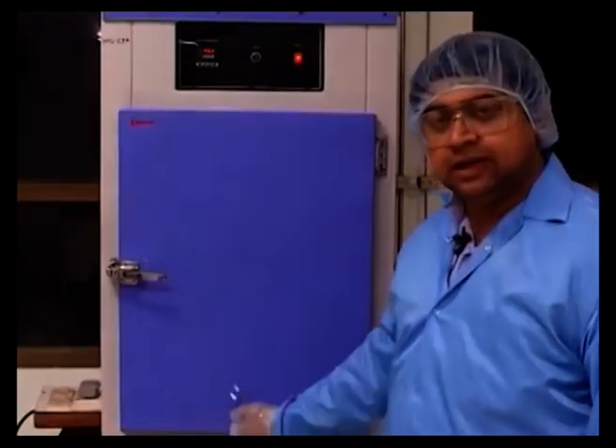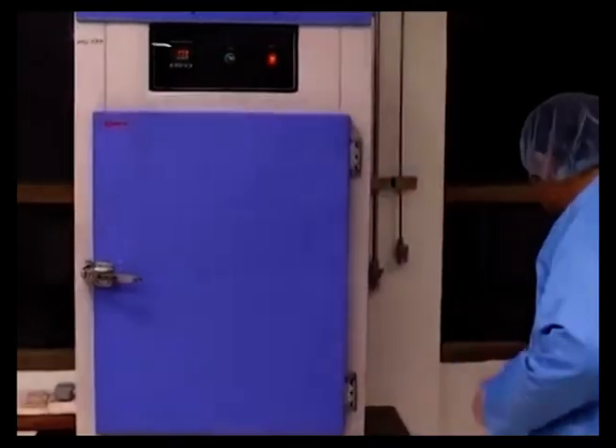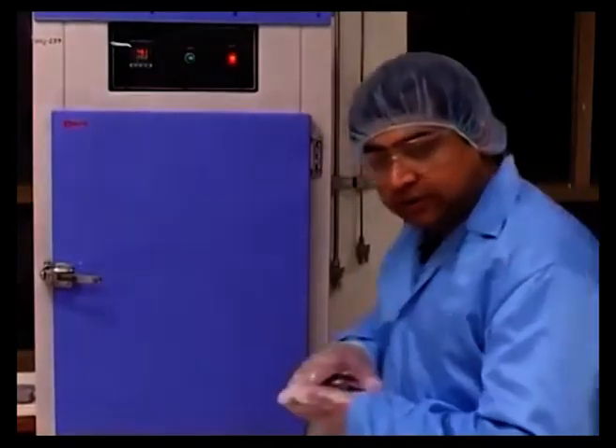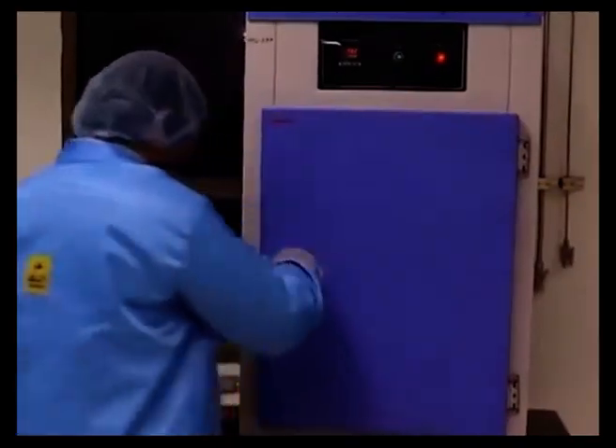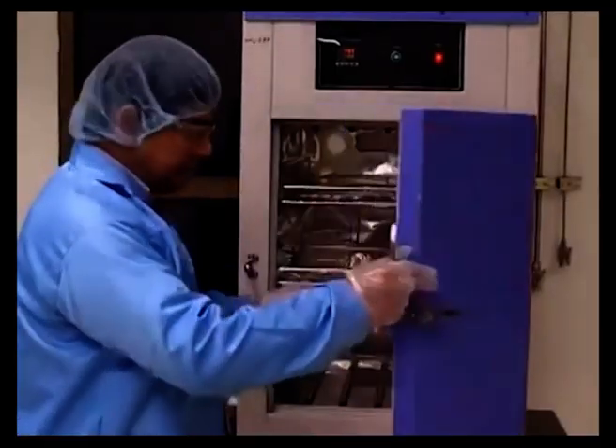So we keep the wafer in the oven for dehydration for about 10 to 15 minutes at about 99 to 100 degrees Celsius. The next step is to unload the wafer and start doing what we call spin coating of the photoresist. So what I am going to do is to just unload it and carry it back again.